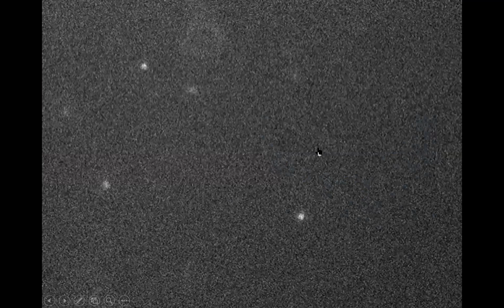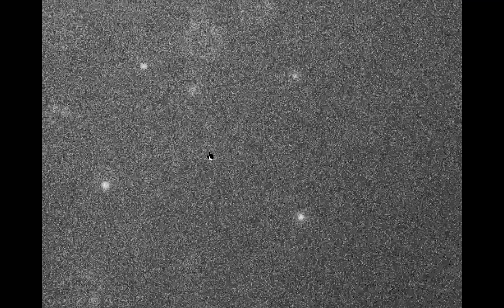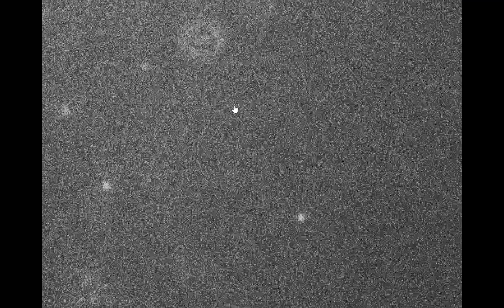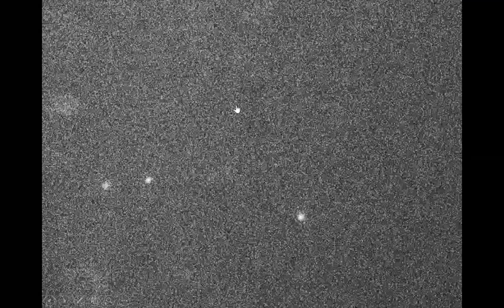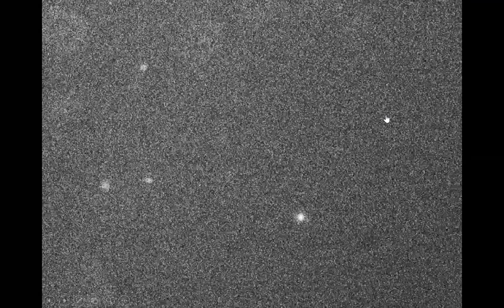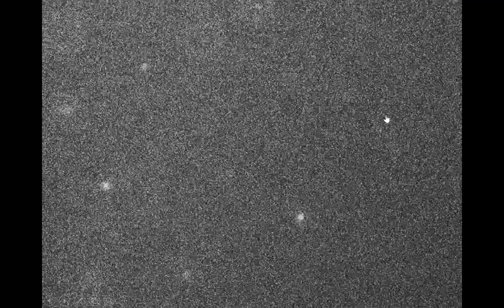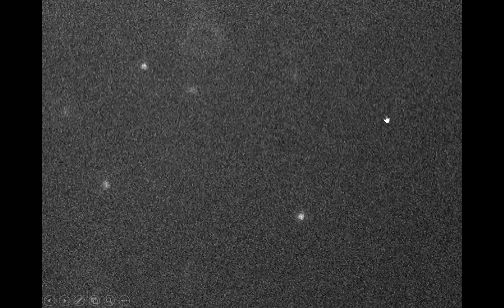Then we go to these quantum dots. The diameter of a quantum dot is about 7 nanometers. Then probably you see this motion. And then we are able to extract the viscosity, I mean, the local viscosity of this gelator solution. And the resolution is about, let's say, less than 10 nanometers. So we are combining what we got on the basis of this particle tracking experiment with scattering experiments using synchrotron radiation and so forth. So, okay, let me skip this.